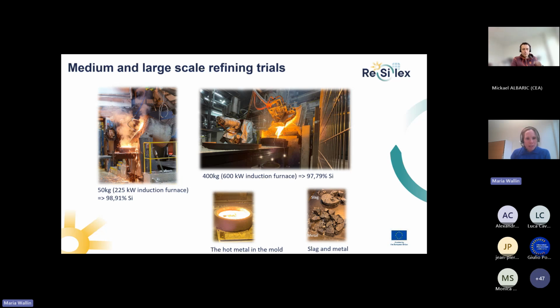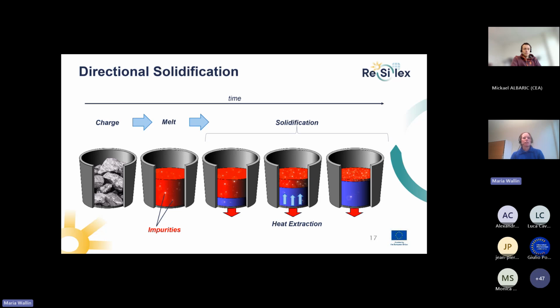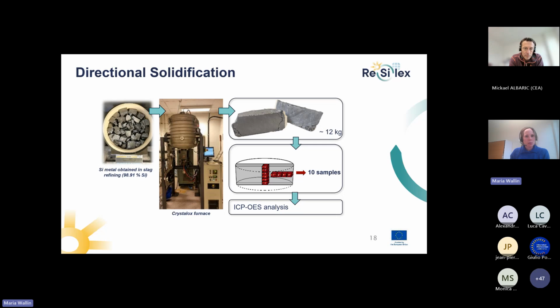So this metal then, we did this directional solidification process. So we put it into our ladle, and you can see it's mixed with impurities. And the theory behind this is that you slowly solidify it from the bottom. So the impurities in theory should end up at the top, as you can see there to the right, the reddish part. And that's what we did. Here you can see our furnace. We produced about a 12 kilo ingot, and then we took 10 samples to the middle and to the side to understand how pure our final ingot was.